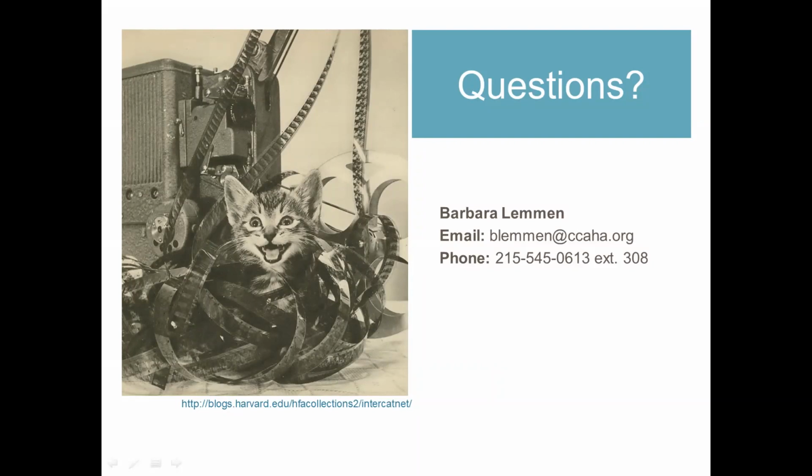Okay, what is the difference between PAT tested envelopes and acid-free paper-based envelopes? Will my collection be damaged if I use the acid-free ones? Well, the acid-free doesn't tell us everything we need to know. I'm glad you mentioned PAT. Usually with well-known recognized suppliers, if something said it's PAT tested in the past, it's safe to use with photographs. Acid-free paper just means that it has a pH that's below 7, and that's not enough information. You may not see damage for a while, but long-term, it's going to potentially cause staining and other problems with photographs because of the off-gassing from the cardboard. I know that the quality materials are much more expensive.